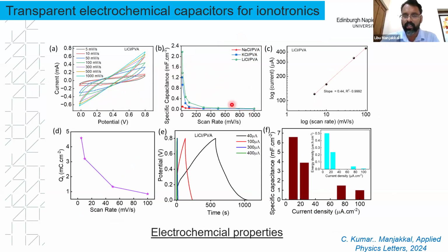Then we measured the capacitance of the device, and you can see here that LiCl shows a very high capacitance. Then we analyzed how much charge can be stored in this type of device, and we found that the lithium chloride-based devices vary with the scan rate. At a very low scan rate, we get almost 4.5 millicoulomb per centimeter square. Then we further calculated the charging and discharging of such devices to implement them as capacitive-type sensors. You can see here how the transparent electrochemical capacitors vary at different current densities, and the variation of energy density and power density.